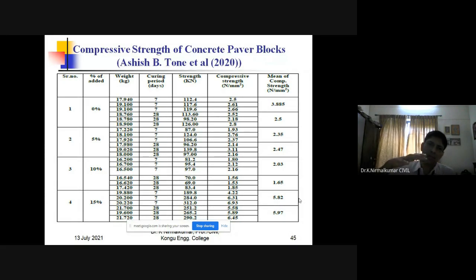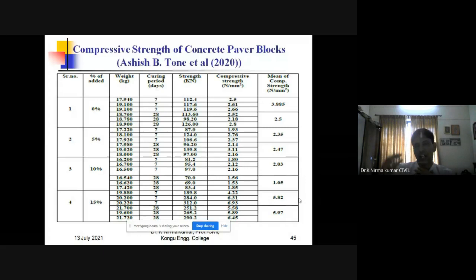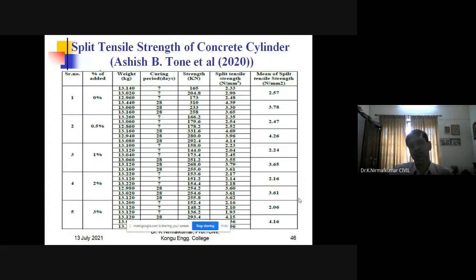Since the paver block thickness is maybe 60 mm, or it may be a little bit lower than 60 mm thickness, the strength, in comparison between the 0% and 15%, you are having the difference. So this is pertaining to the paver blocks. And this is for the tensile strength. We have carried out the experiment for the tensile strength.